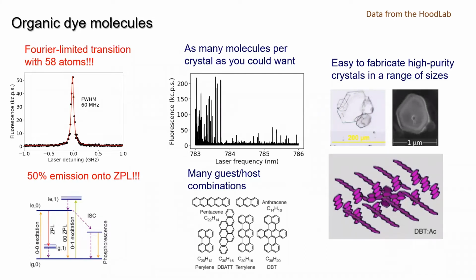But miraculously, once again, it was demonstrated in the 90s by Michel Orrit that an organic molecule inside an organic matrix at liquid helium temperatures can demonstrate a lifetime limited transition. Once again, that means that when you cool it down enough, the dibenzoterrylene molecule in this case is strongly enough connected to the lattice that it doesn't move, right? It's not jumping all over the place, but it's loosely enough connected that you can actually decouple it from all the phonons jostling it around. And then it acts as if it's just a molecule floating inside some vacuum chamber. And you can actually achieve that, which is quite remarkable.